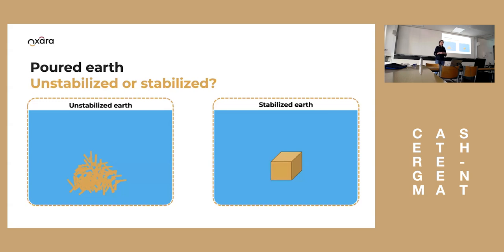The way we see it, unstabilized earth is an earth that is not water resistant. It's still soluble in water, and it dissolves, as its strength mechanism is only the drying. So if it only dries and gets its strength, then it also means that if it's in water, it dissolves. And this is unstabilized earth. If you introduce a reactant or a chemical that consumes water and reacts with the water, and it binds the water, and then it also binds the clay platelets, more or less depending on the dosage, then you can put it into the water and it will not dissolve anymore.